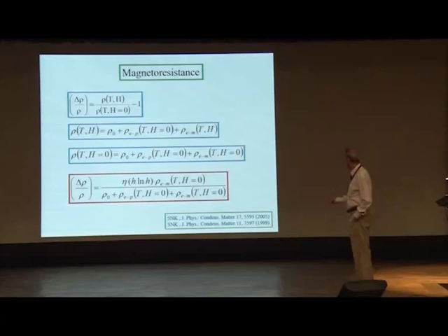In this expression, the only variable is eta. Eta only provides for the surface spin disorder, and how that changes when you apply an external field, and how the electron-magnon scattering at the surface would take place. So there will be some extra contribution coming from the surface, which is not accounted for in theory. Theory was done for a homogeneous system where there was no disorder, so this is just to take into account the disorder.